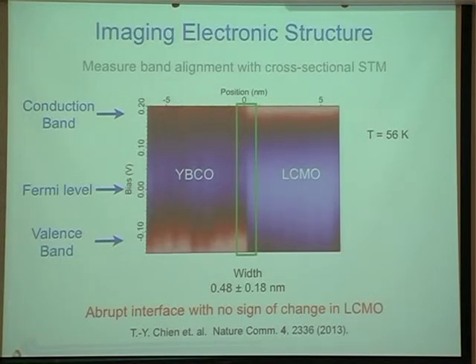Like I mentioned, we have no model for these kinds of systems. Now, using this kind of approach, we can actually measure the band alignments. So in this case, the conduction bands were aligned. Here's the Fermi level. I have the valence band of the cuprate here, the valence band of the manganites a little further down here. It's not shown on the structure.